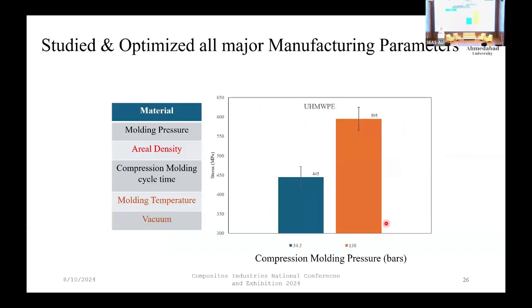I mention pressure because for temperature, the processing temperature might be defined by the OEM, the supplier of the raw material. In a study, we performed the compression molding at a pressure of 34.5 bar, keeping the grade constant, and for obvious reasons I can't declare the grades here. We found that the strength of this material is somewhere around 450 megapascal. Then, with the temperature remaining constant and the processing time at 30 minutes, we increased the pressure by 4 times.